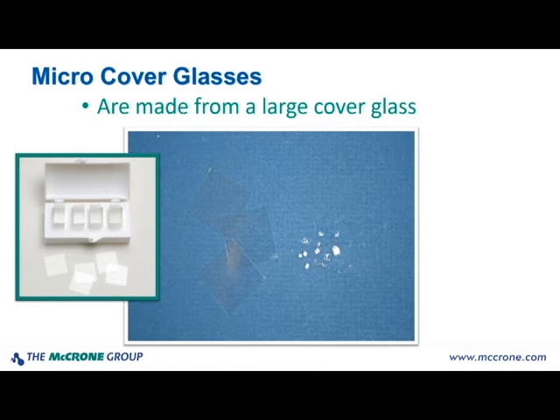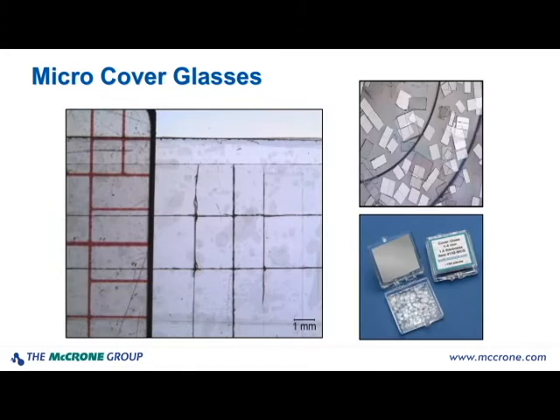The micro cover glass method requires small micro cover glasses, as you see here, which are actually made from your standard large cover glass. Most everybody has a large cover glass laying around, so you can make these yourself. You do this by scoring one side of the large cover glass with a diamond scribe in both the vertical and horizontal direction. This gives you the ability to make them as large or small as you need.